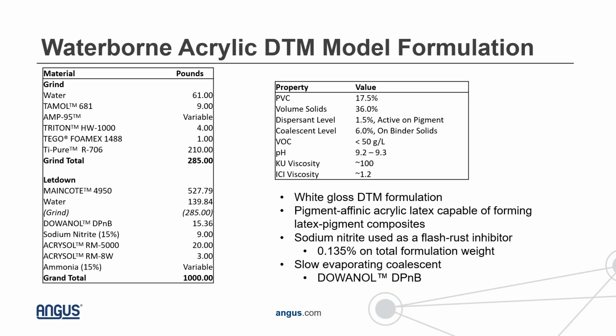And so we took a look at this. We did this through a waterborne acrylic direct to metal formulation. This is a very standard formulation that we used. This happened to be based on the Maincote 4950 resin from Dow. It's essentially a white gloss direct to metal coating formulation at around 17.5% pigment volume concentration, 36% volume solids. This is a less than 50 gram per liter VOC formulation. This binder in particular is a type of latex that is pigment affinic, and so it can form latex pigment composite particles. We used sodium nitrite as our flash rust inhibitor, and we also used Dowanol DPnB as our coalescing agent. This is a slower evaporating solvent. Our pH target for this formulation was around 9.2, KU viscosity target around 100, and ICI around 1.2.